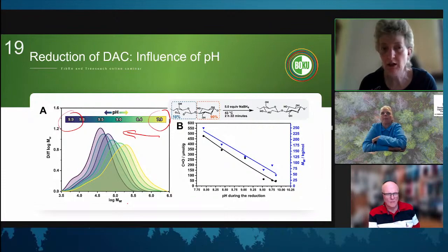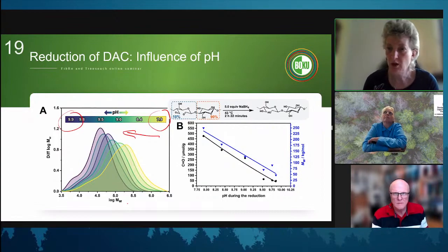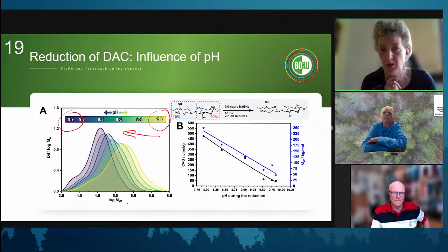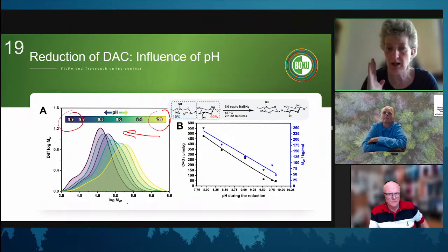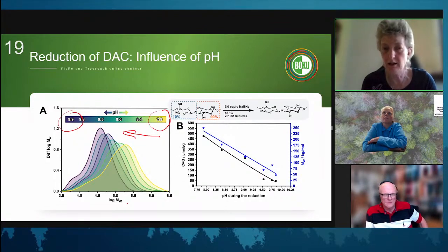And we look a lot into that, and we also have processes which we call diagnostic beta elimination. So we do beta elimination in order to figure out where at the cellulose backbone oxidation has occurred. If my oxidation is hypothetically in the middle of a chain and you bring that into an alkaline environment, you split this chain into 2 halves. So you have a large drop in molar mass.